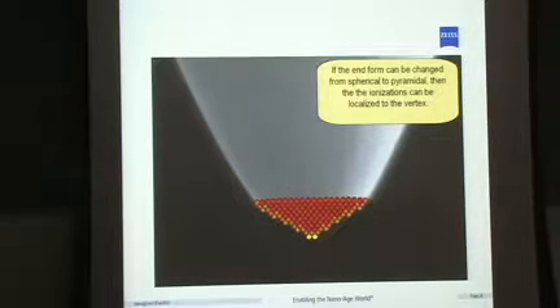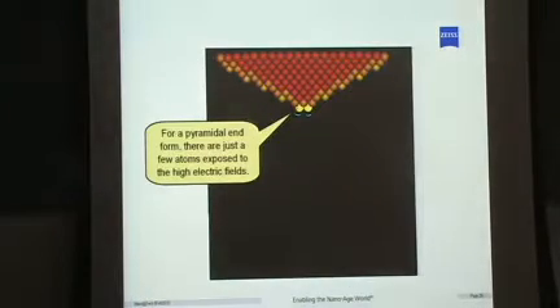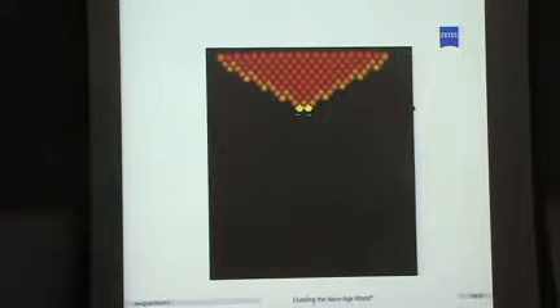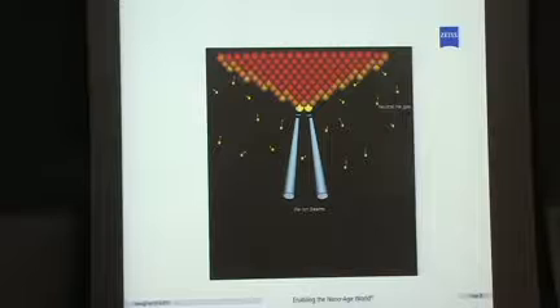If you play the right music, you can get the atoms to dance around, and when you turn off the music, they'll stop dancing and they'll leave themselves in these nice planar forms. So instead of a polyhedra of many facets, you can just get 3 facets, essentially a 3-sided pyramid at the end of this needle. Now when you turn on the electric field, you don't have a ton of these little ionization disks, you just get them at the terminal atoms, 3 of them for a 3-sided pyramid. And you just get a small number of beamlets coming out.